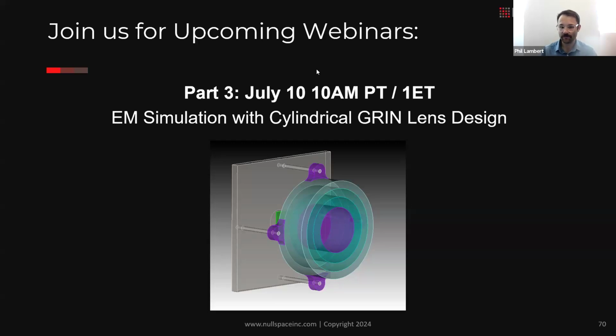We've run through a number of other device designs with some of our partners and customers. And what we tend to find is that the gyroid's performance as a lens matches the simulated performance in every case. The area where things start to break down is as you start to get closer and closer to your cutoff frequency. So as you try to squeeze out just that last little bit of performance up at the upper frequencies, you have to keep your eye on the cutoff there.